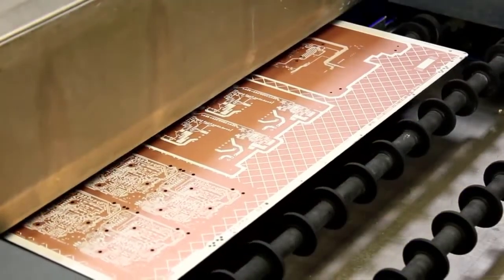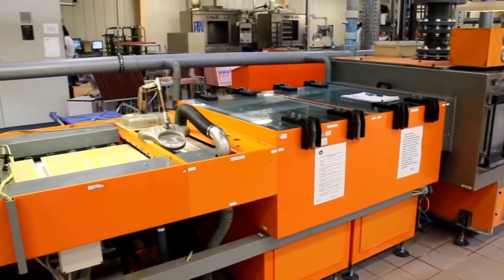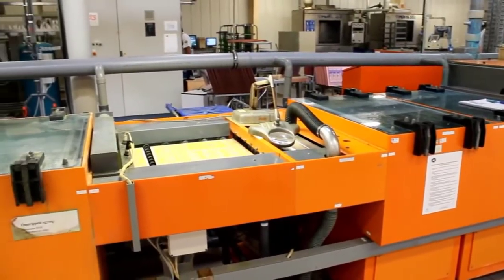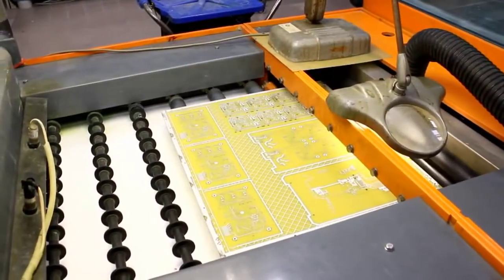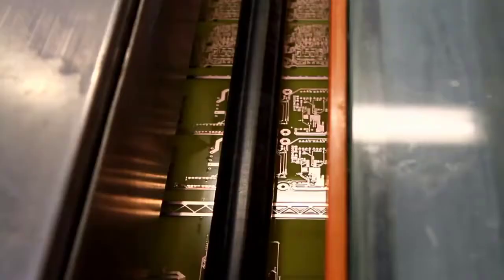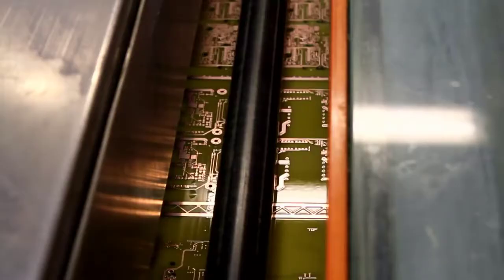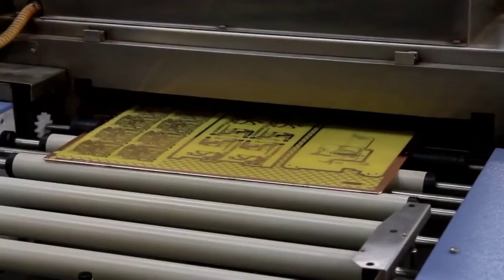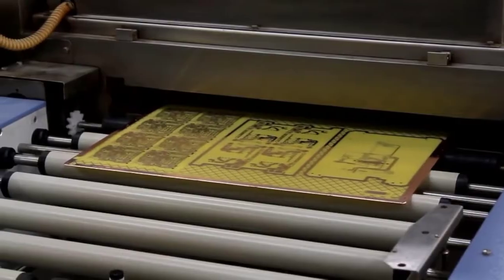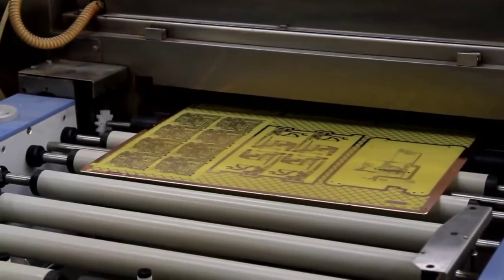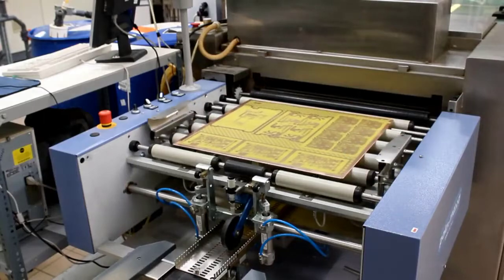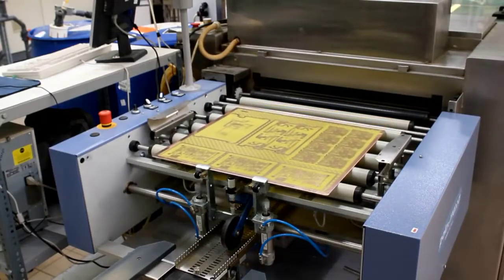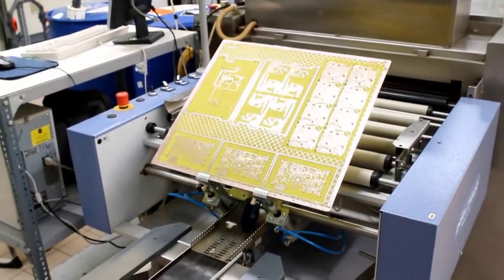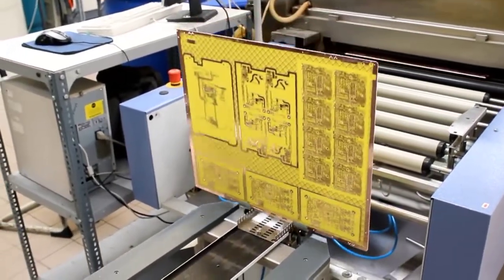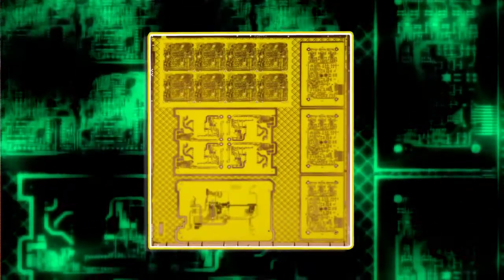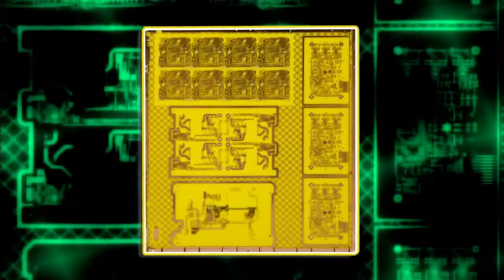The first step is to dissolve and wash off the resist which covers the unwanted copper. Then we remove the unwanted copper using a powerful alkaline solution to etch away the exposed copper. The process is carefully controlled to ensure that as we etch down, we don't etch sideways as well. This means that the finished conductor widths are exactly as designed. But designers should be aware that the thicker copper foils need wider spaces between the tracks. Finally, we strip off the thin tin coating which protected the copper image, so now you can see that only the designed copper pattern remains. As the boards emerge from the line, they are stacked automatically.